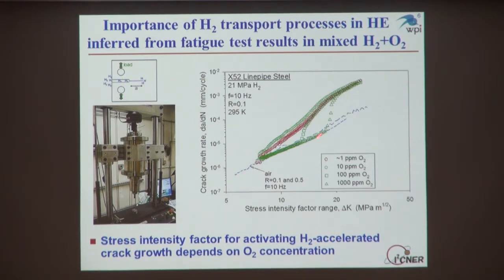And then in these different hydrogen environments, and I'll explain the difference here, what we see is that as we increase the stress levels on the material, at some point we start to see the crack growth rates accelerate. And by accelerate, I mean that their growth rates are above those that we would measure in air, which is just due to mechanical driving forces. And what I'm showing you is that these experiments were done in high purity hydrogen, but also in hydrogen with small amounts of oxygen impurities.